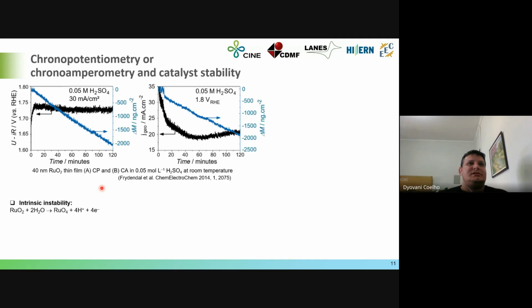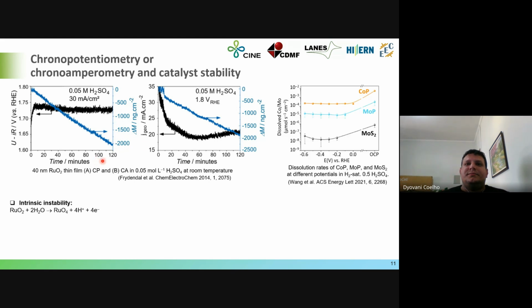But actually, they used this kind of technique coupled with the electrochemical quartz crystal microbalance. And here in blue, you can see that the catalyst is constantly dissolving over time. So the catalyst is not stable at all during operation, even though the chronopotentiometry claims that the catalyst is stable. So we need more sensitive techniques to verify whether the catalyst is stable or not. Here, they claim that ruthenium oxide is intrinsically unstable during operation. And we have other kinds of examples using, for example, catalysts for hydrogen production.